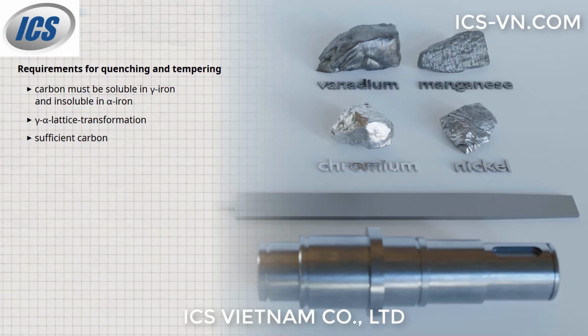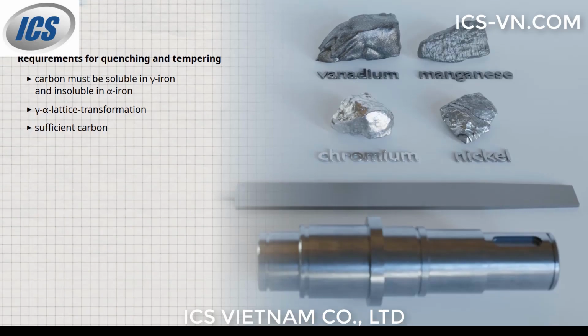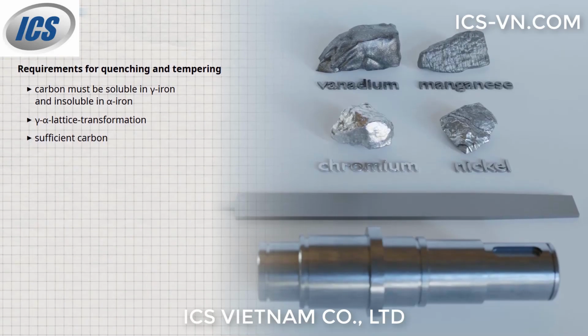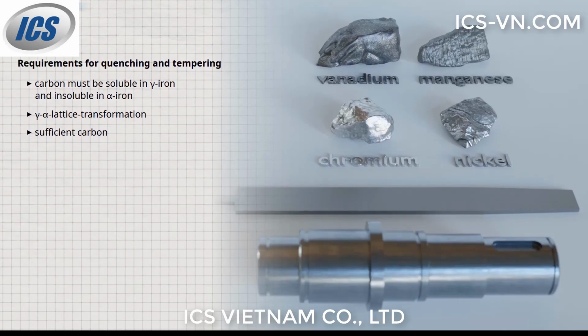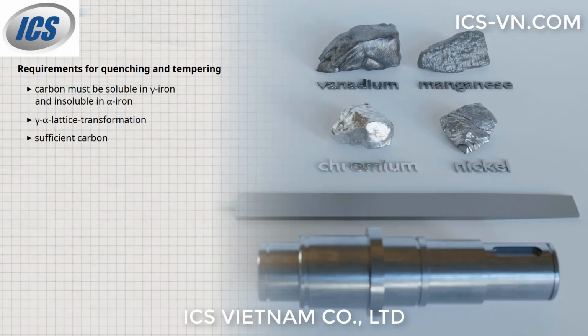Too little carbon would result in no significant martensite formation. Although there would still be a small increase in hardness or strength, this would not justify the relatively high cost of the process. As a guideline, hardening is only economically and technically feasible from a carbon content of about 0.3%.